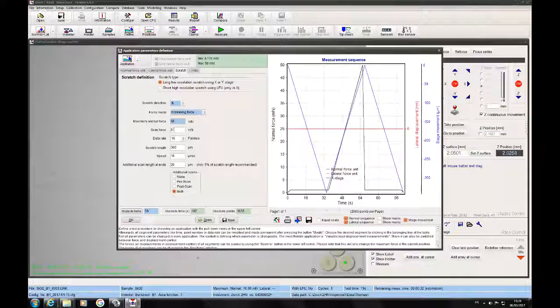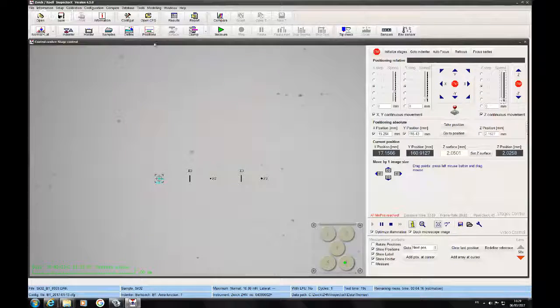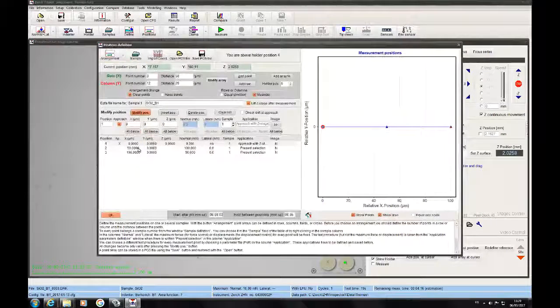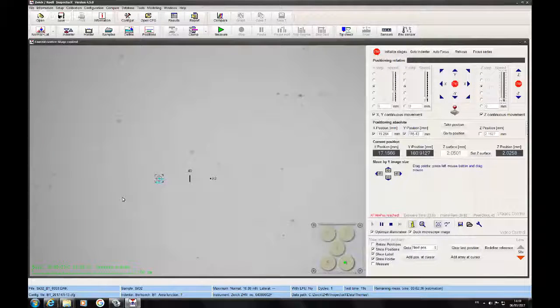We use a pre and post scan with a small scan force of 300 micronewton, and the distance maybe 250 micron. Speed is 10 micron per second, and that's it. And we need only 1 point for the scratch and 1 point for the approach with a mechanical stage. We can also drag the point in the optics with the mouse if you want.